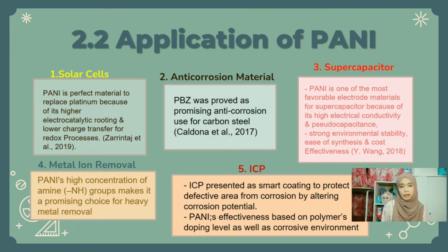Let's proceed to the application of polyaniline. The first one is the solar cell. Platinum is the most expensive component in the solar cell. PANI is the perfect material to replace platinum because of its higher electrocatalytic activity and lower charge transfer rate for redox process. Microporous PANI electrode performs even better than platinum electrode. PANI porosity reaches the specific surface area of liquid electrolyte in solar cell, improving catalytic activity and trapping efficiency.